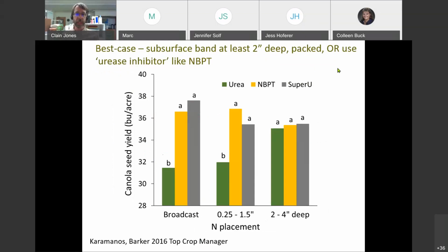Something else that you can do, like I mentioned, is apply a urease inhibitor or put your nitrogen deep enough where it won't volatilize. This was a study done on canola where nitrogen was either broadcast, placed 1/4 to 1.5 inches deep, and this is after packing, or 2 to 4 inches deep. What it shows is that for broadcast products, there was a major disadvantage of using urea and a major advantage of using these two products that have a urease inhibitor in them. The urea sat on the surface and volatilized.